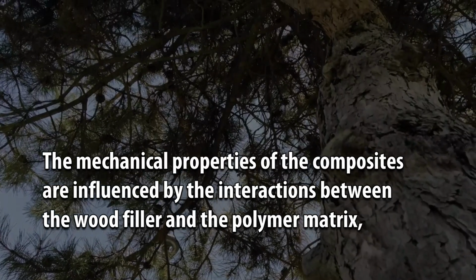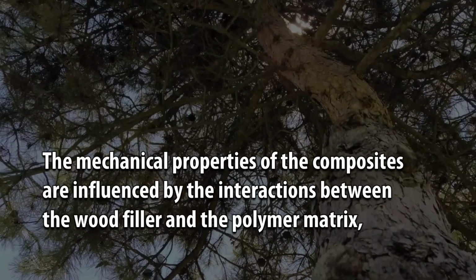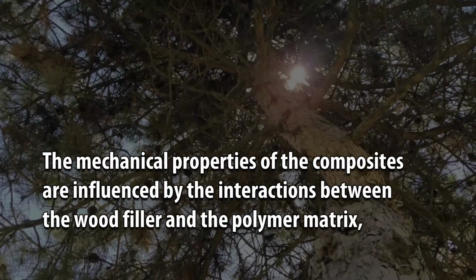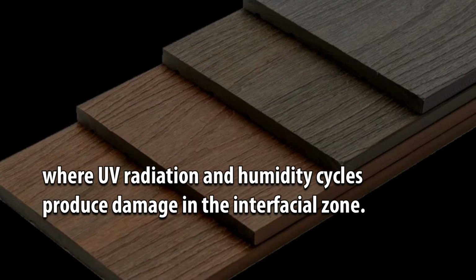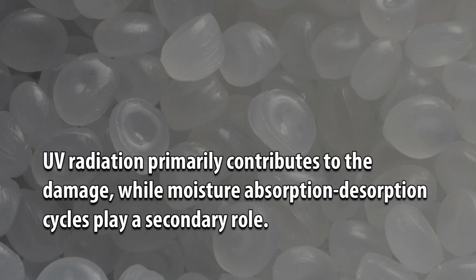The mechanical properties of the composites are influenced by the interactions between the wood filler and the polymer matrix, where UV radiation and humidity cycles produce damage in the interfacial zone. UV radiation primarily contributes to the damage, while moisture absorption-desorption cycles play a secondary role.